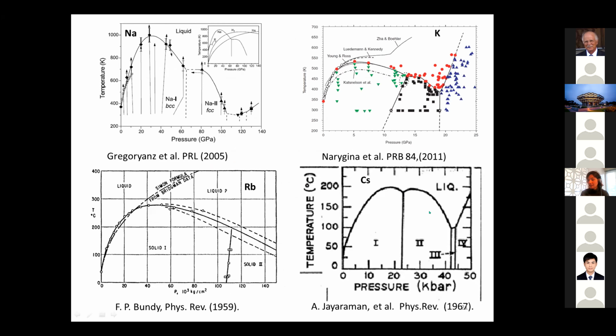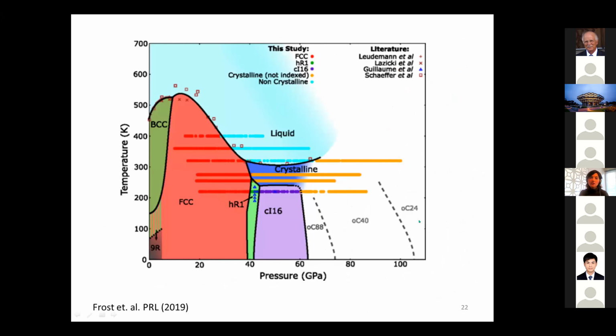That is not necessarily originated in the quantum effects, and I can say probably not very much in the case of something like cesium that is very heavy. And this is true for the melting curve of lithium. This is a work that has been done at APS by Frost et al. a couple of years ago. But the squares are the studies that we have done a few years ago on the melting line of lithium.